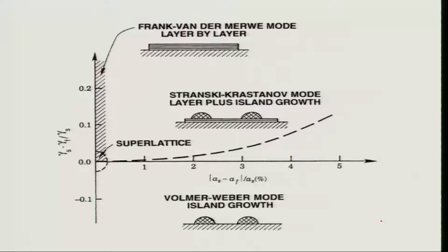Which then again confine electrons in that size, which is a quantum dot behavior. Now, all this information is presented in this view graph, which relates which growth mode would be more stable given the difference in surface energies and lattice mismatch. It also signifies the region where we should be depositing if you want to deposit super lattice.